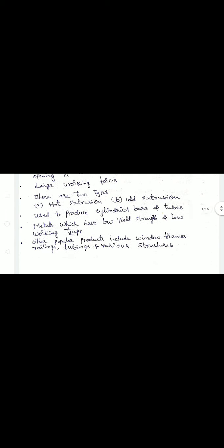Ferrous materials, which have high yield strength and high hot working temperatures, are difficult to extrude because of the high extrusion forces required, as they have a tendency to stick to the die and container walls under high compression, pressures and temperature conditions. However, with the use of high temperature lubricants such as phosphate based and molten glass lubricants, ferrous alloys including stainless steels are being extruded now.